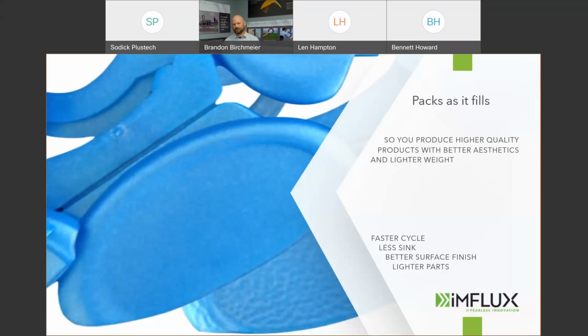And our philosophy is pretty simple. Why create the defects and go back and fix them with extra time and pressure, which is basically what's happening in your conventional process? Once those parts are filled, you now need to fix everything you created during the filling, all those sinks, all the orange peel. You need to pack that part out, right? That's what we transfer into a pack and hold stage. However, if you fill and maintain constant pressure in your process, those parts will actually pack themselves out while that flow front progresses. So now I don't have to go back in and fix the sink or fix the surface appearance after the fact and after transfer. Now it's happening while that part's being filled out.